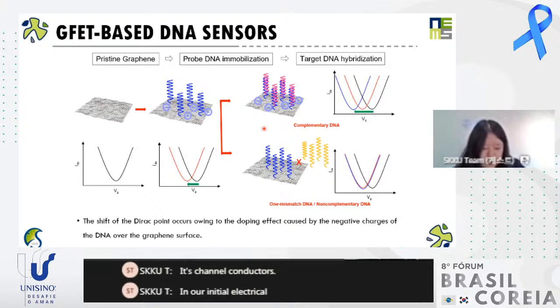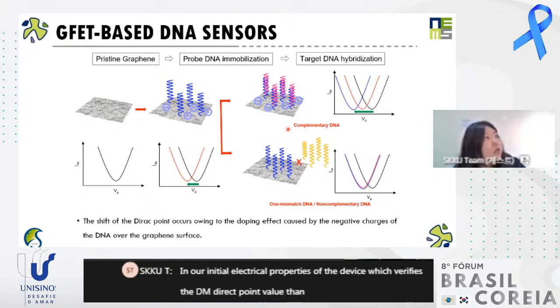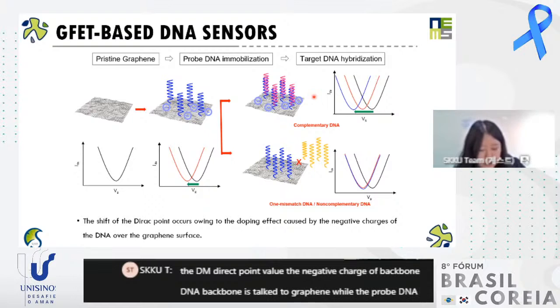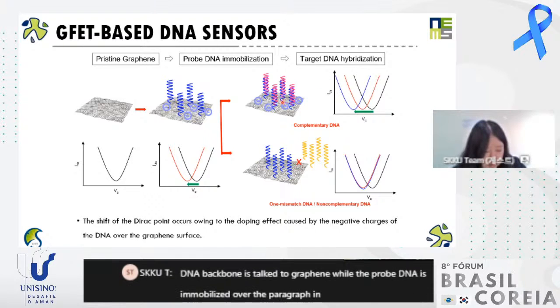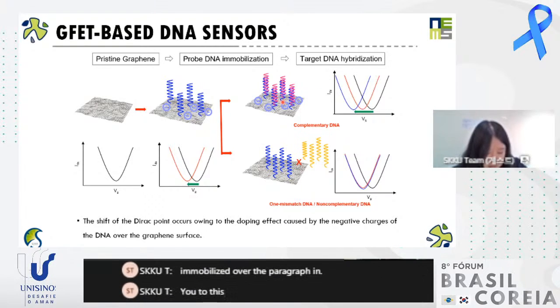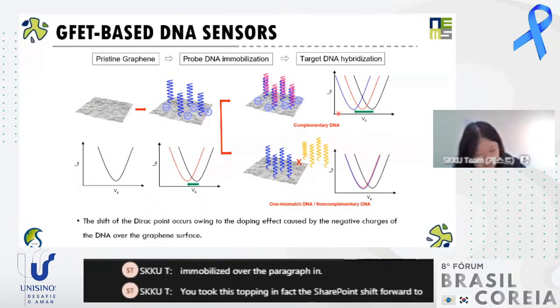In the initial electrical properties of the device, which verify the Dirac point value, the negative charge of the DNA backbone is doped to graphene while the probe DNA is immobilized over the bare graphene. Due to this doping effect, the Dirac point shifts toward the negative value.